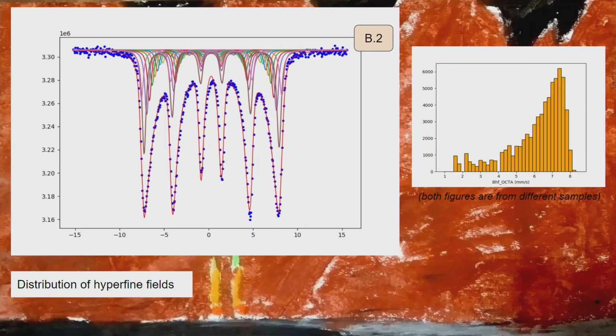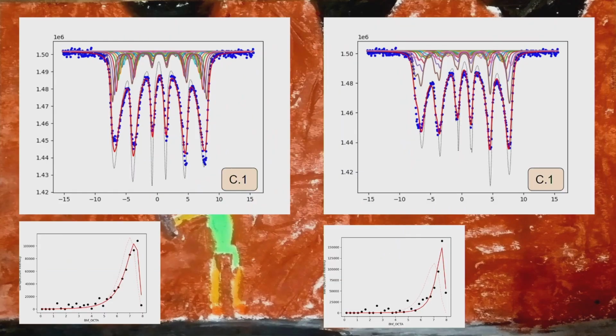Okay, here is one of the spectra that was fitted considering a distribution of magnetic fields, but taking the isomer shift fixed, as only the magnetic field is affected by collective excitations. And we have a relatively good spectrum. We have some difference here, some difference maybe here, but it was well fitted. In fact, the isomer shift, I don't have it here, was not exactly the one of maghemite, it was a little higher. But the fit is good.